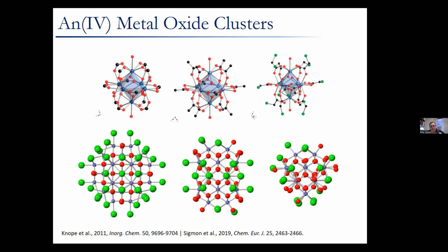And then at the bottom of the screen, you can see the additional hierarchy that we've identified for plutonium, where we have a plutonium 16, a plutonium 22, and a plutonium 38 metal oxide cluster. And I'll note that the 38 cluster has also been identified for uranium and neptunium. But the difference there is that the uranium and neptunium species required organic ligands as capping agents, whereas the plutonium just requires these chloride ions as capping.